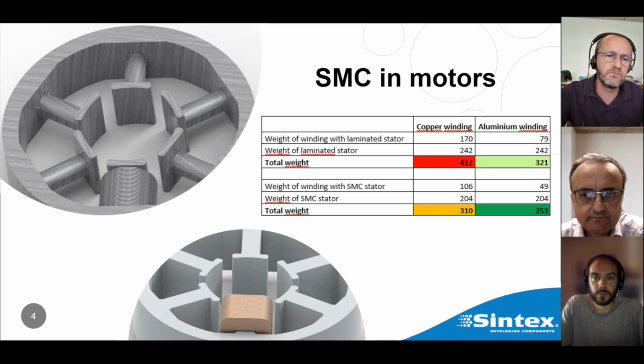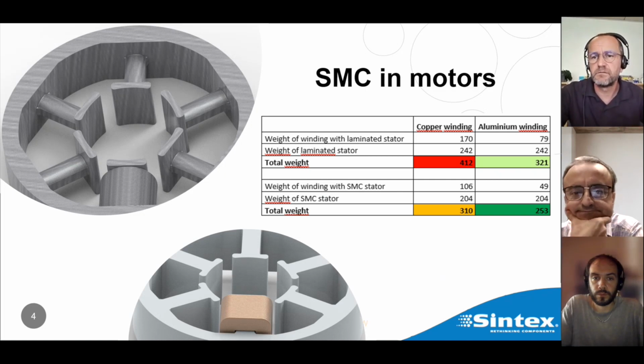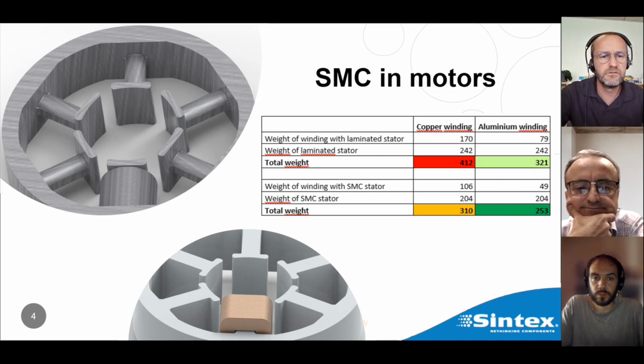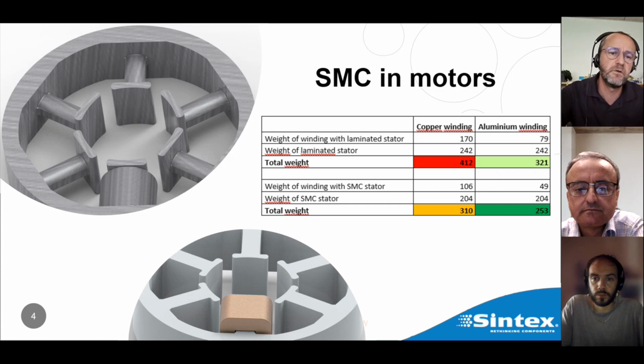In this case, we tried to simulate the weight, and you can see in the table that going from laminated to SMC stator, just by changing the design, we can reduce the weight from 412 to 310 grams for the stator. If we change to aluminium for the winding, to reduce weight even further, the weight of the SMC component combined with aluminium could be reduced even further, down to 250 grams.